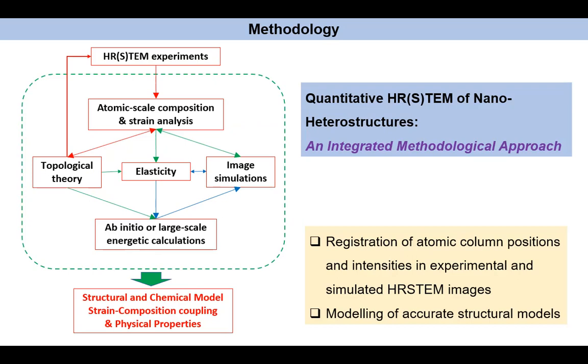So this is our integrated approach. In other words, starting from the experimental observations, we try to obtain the atomic scale composition and the strain at the nanoscale. To do this, at the first stage we perform topological, in other words, crystallographic analysis, and also elasticity theory, as well as possibly image simulations. All this information is combined with modeling by ab initio or large-scale energetic calculations, for example, by molecular dynamics. And there is an interaction between experiment and theory in order to arrive finally at the accurate structural and chemical model, as well as the strain composition coupling, and to correlate this with the physical properties.